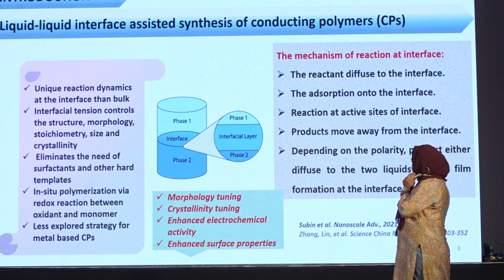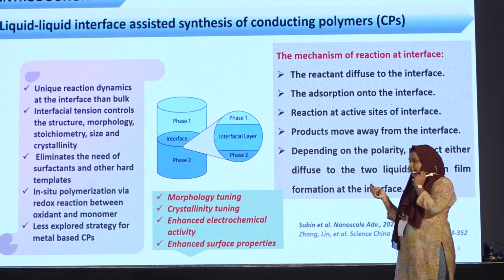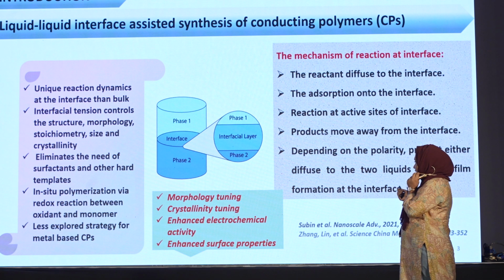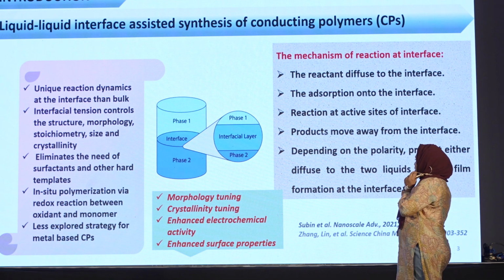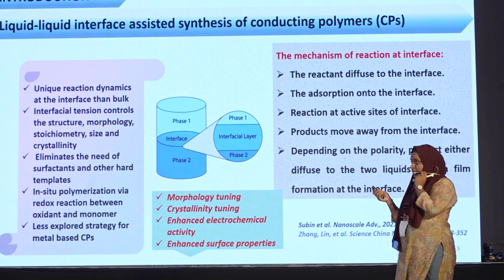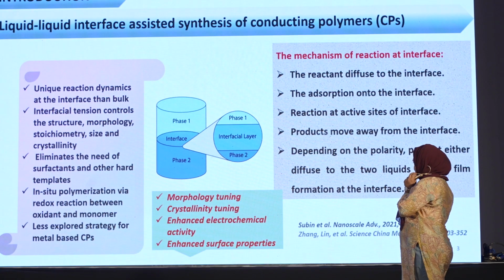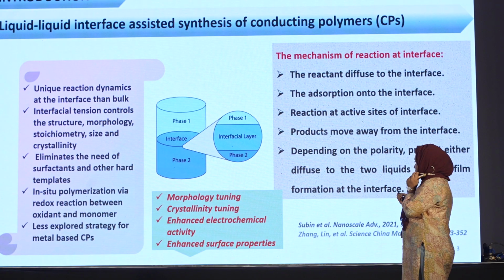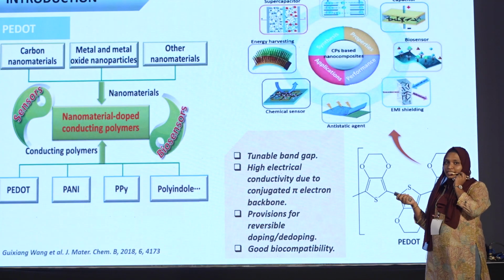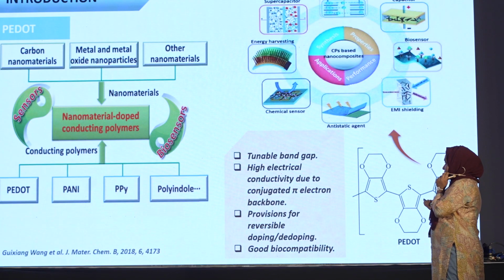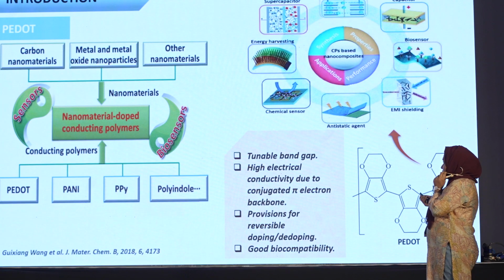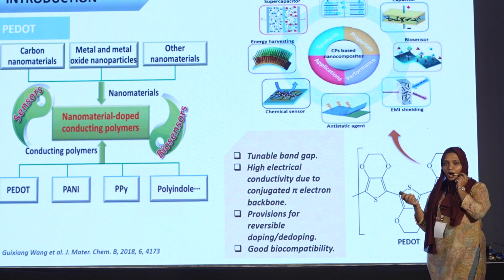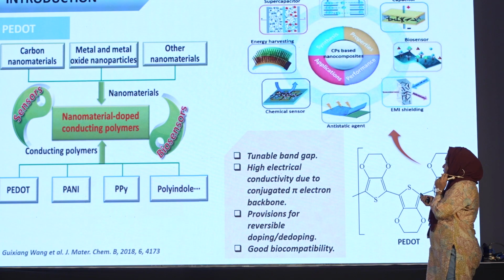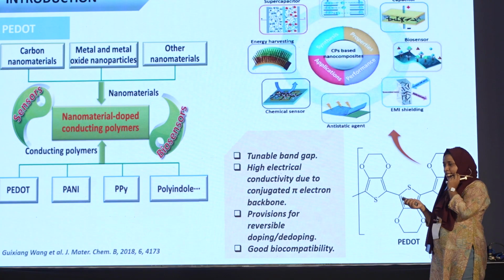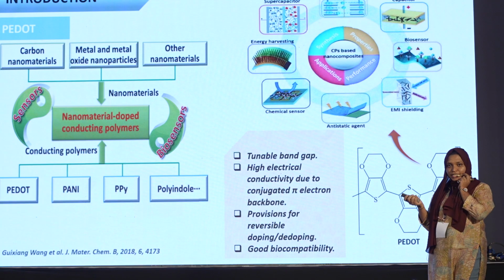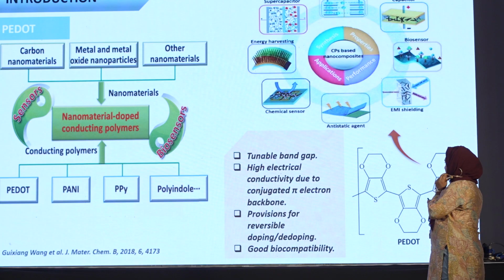In a liquid-liquid interface synthesis, the interface acts as a quasi 2D template for the monomers and oxidants to diffuse and meet at the interface, and the polymerization reaction is triggered. For the synthesis, I have chosen a well-known conducting polymer, poly-3,4-ethylene dioxythiophene, commonly known as PEDOT, due to its excellent film-forming properties, good stability and tunable conductivity.